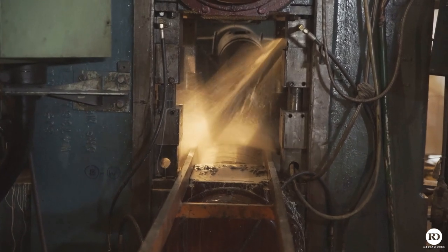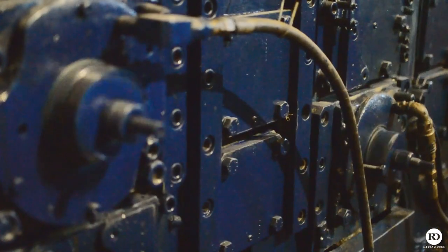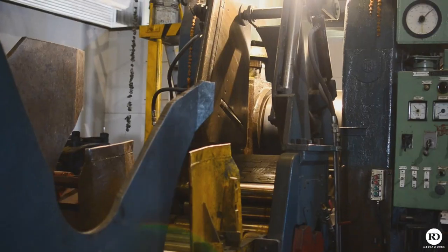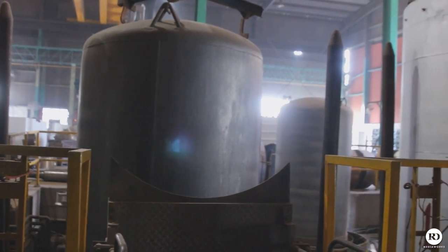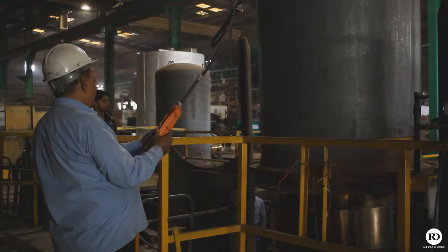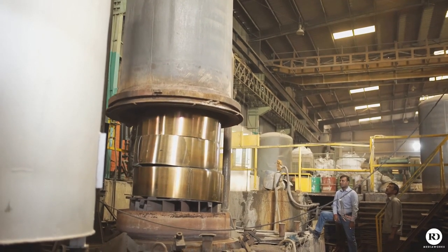The strips are thereafter intermediately rolled from 16 mm down to 3.5 mm on our state-of-the-art Farmer Norton and Loewy Robertson automatic cold rolling mills. Thereafter, the strips are annealed in Bell annealing furnaces under inert atmosphere of hydrogen and nitrogen. The annealing temperature and cycle time depends upon the coinage alloy being produced. The annealed strips are pickled and then slitted and made ready for final rolling.